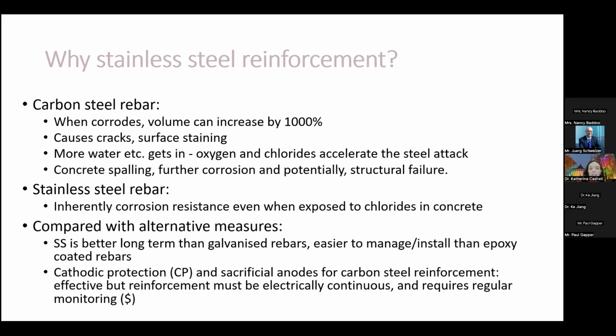On the other hand, of course, stainless steel reinforcement doesn't corrode typically, and its inherent corrosion resistance, even when exposed to chlorides in concrete, is what makes it so valuable for this application. There are other measures for tackling the corrosion problem in reinforced concrete. But studies have shown that using stainless steel as a reinforcement can provide a better long-term solution than galvanized rebars, for example. It's easier to manage and install compared with epoxy-coated rebars.